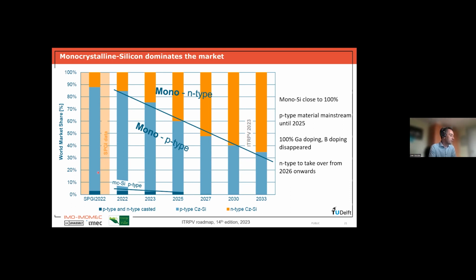So if you look to the situation in 2022, you see here the blue, that is actually P-type Czochralski silicon, so monosilicon. The orange, that is N-type Czochralski silicon. I will explain later why people are switching slowly from P-type to N-type. And the dark blue you see here, this is actually P and N-type multicrystalline. So it's only a few percent and it will completely fade out. That's the prediction by 2025. So the monosilicon wafers are dominating. At the moment, it's P-type, but the industry foresees that more and more N-type wafers will be used.